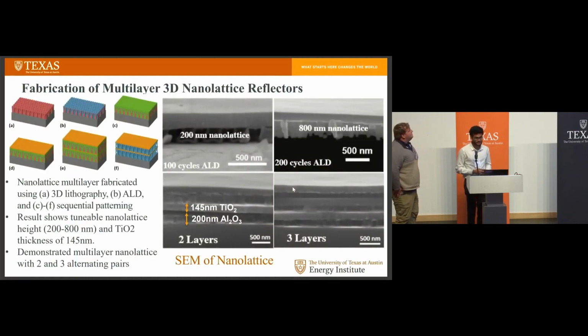Coming to the fabrication of these multi-layer 3D nanolattices, initially we use a silicon substrate over which we place photoresist, and then we pattern hexagonally close-packed nanospheres on top of this photoresist using a lithography process. Then we subject it to atomic layer deposition, which is a conformal coating of aluminum oxide on top of these 3D intensity patterns that are formed. And over that, we place photoresist on top of it to provide a stable base so that the subsequent layers can be stacked on top of it. And over the photoresist, we again place a solid layer of titanium oxide, which results in the formation of figure D from the left-hand side image.